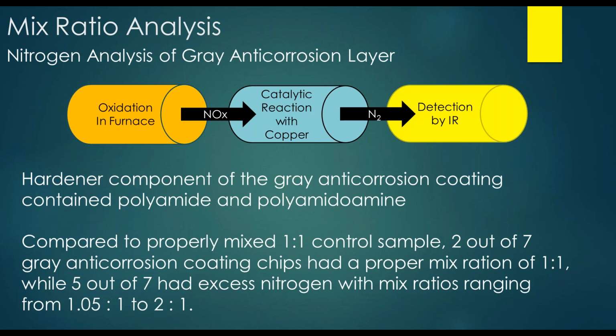When we compared properly mixed one-to-one control samples, we found that 5 out of the 7 samples that we investigated had excess nitrogen, which is indicative of excess hardener. The mix ratio of the hardener to resin components ranged from 1.05 to 1 to as high as 2 to 1.